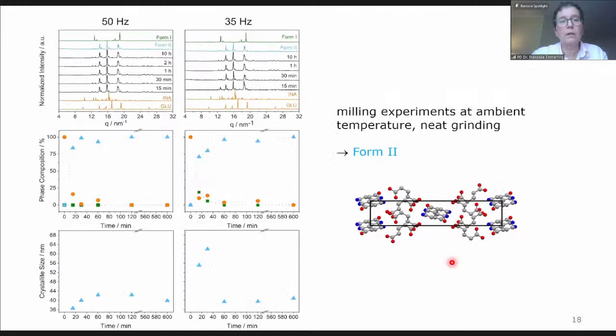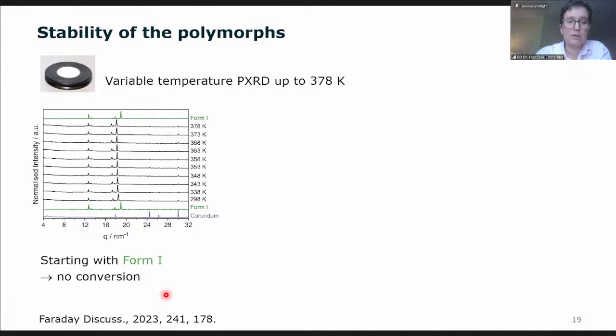So before we started that, we had a closer look at what's actually happening when we neat grind the starting materials. Here you see the data for 50 hertz and for lower frequencies, in this case, 35 hertz. And in both cases, we had a conversion to form two. And you can see that we also end up more or less, shown down here, with the same crystallite size, roundabout 40 nanometers. It takes a bit longer if you use lower frequency, but nevertheless, we never observe another form in this case. Then we did variable temperature X-ray diffraction measurements to see what's happening. If I start with form one and heat it up, you see here the data, then more or less nothing happens. So that is still form one and there's no conversion.